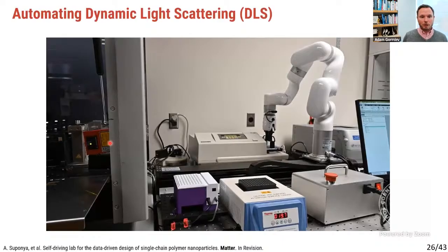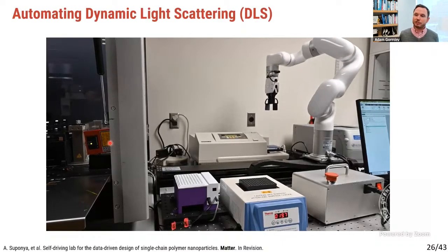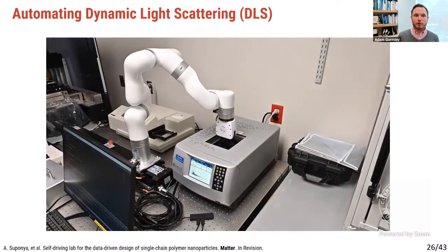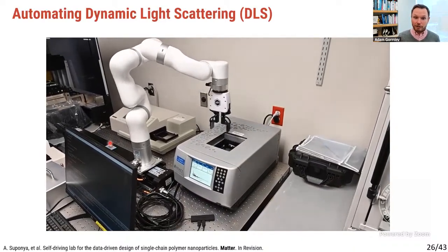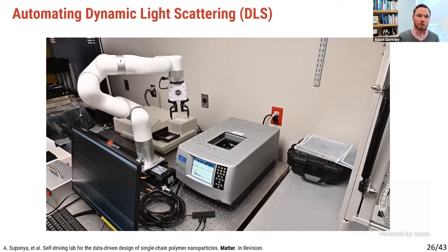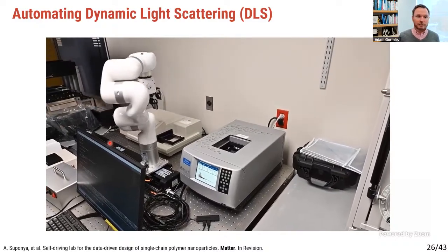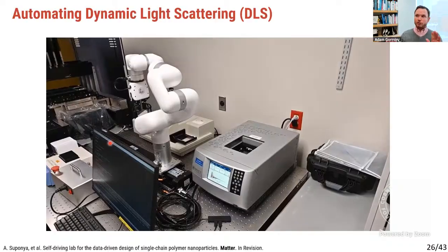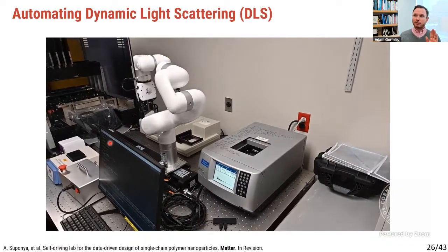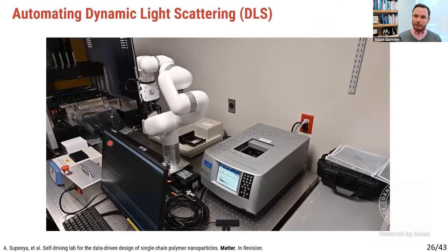And so, although we can't put this system on a beamline at Brookhaven National Lab, we did want to build a self-driving lab using our system. And the obvious analytical instrument to do this was our dynamic light scattering plate reader. It doesn't give you the richness of information that small angle X-ray scattering does, but it does tell you something, and it's automatable. And so we put our DLS plate reader on our automation and built out our self-driving lab for single chain polymer nanoparticles.